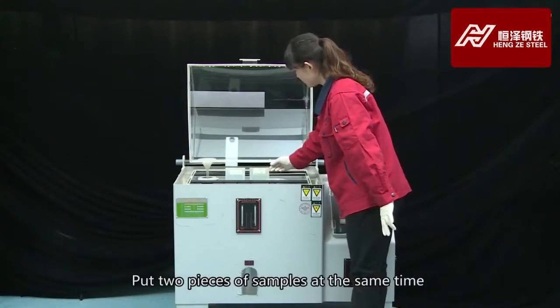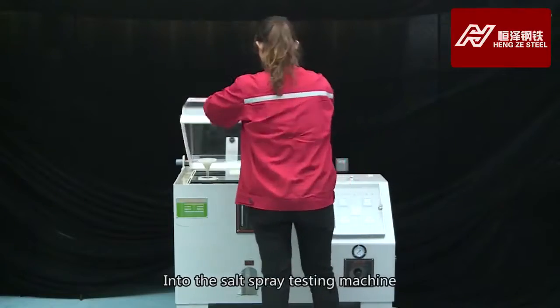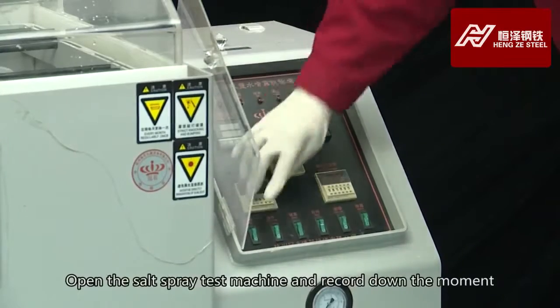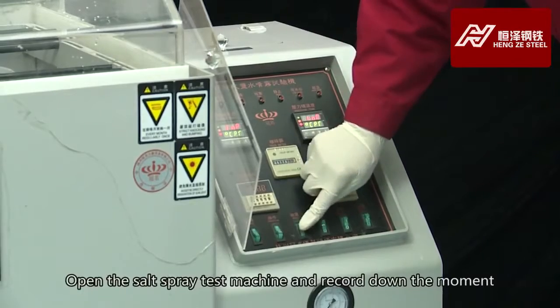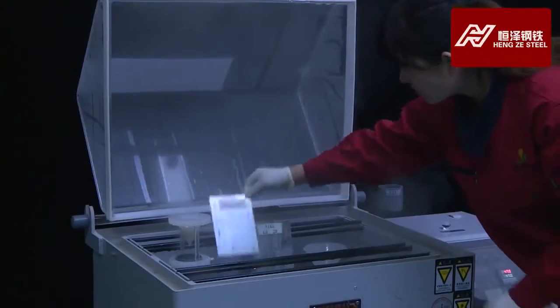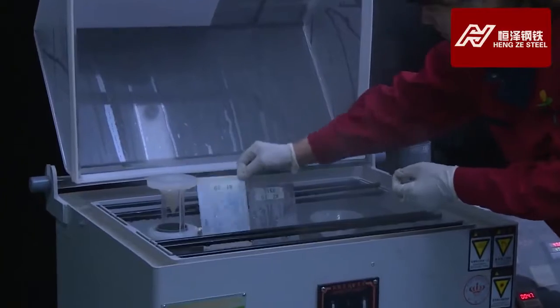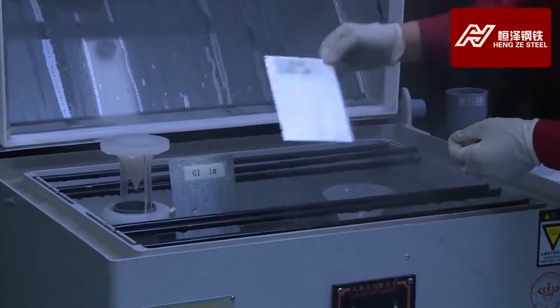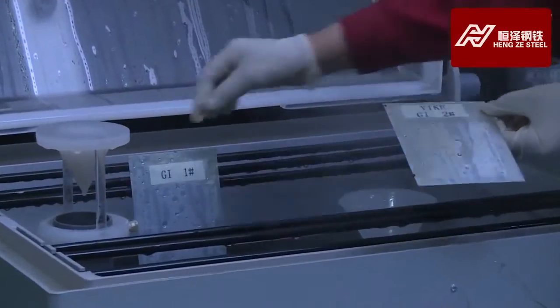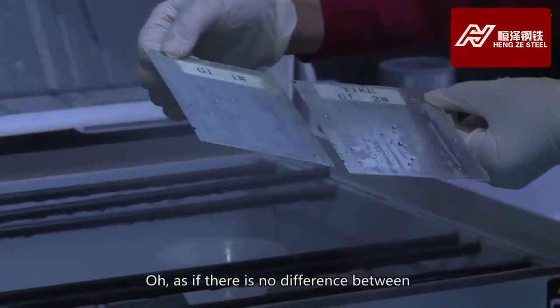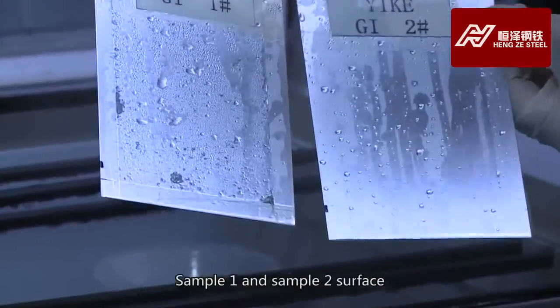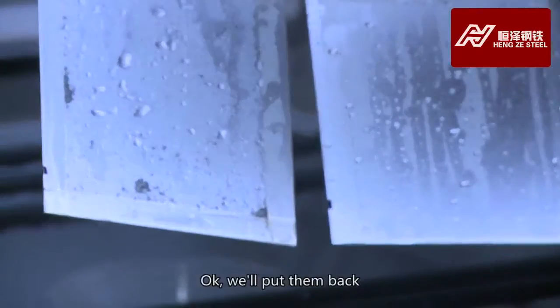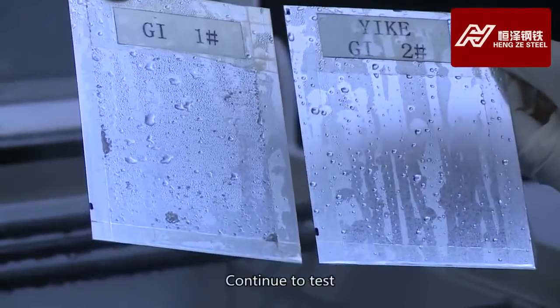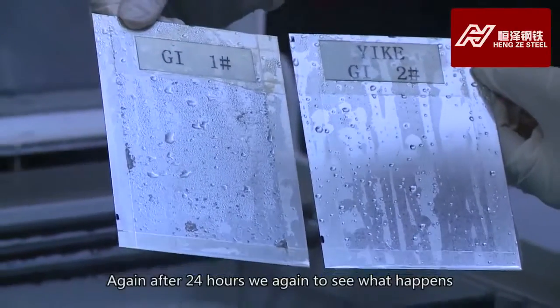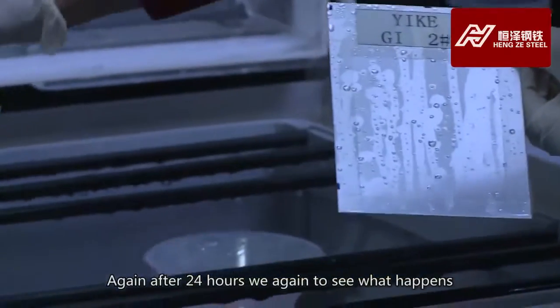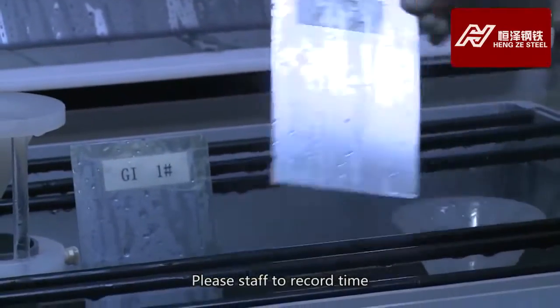Put the 2 samples at the same time into the salt spray testing machine. Open the salt spray test machine and record the moment. Oh, it looks like there is no difference between the surface of sample 1 and sample 2. Okay, we'll put them back and continue the test. After 24 hours, we will look again to see what happens. Please have the staff record the time.